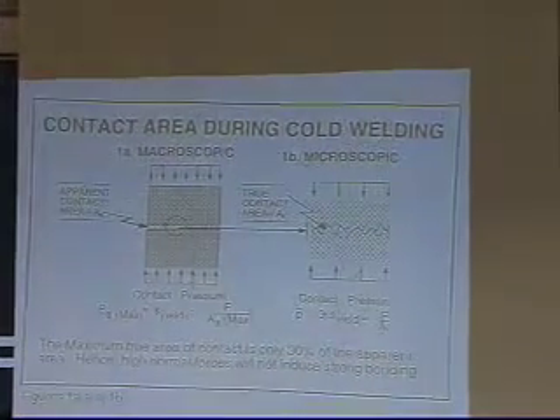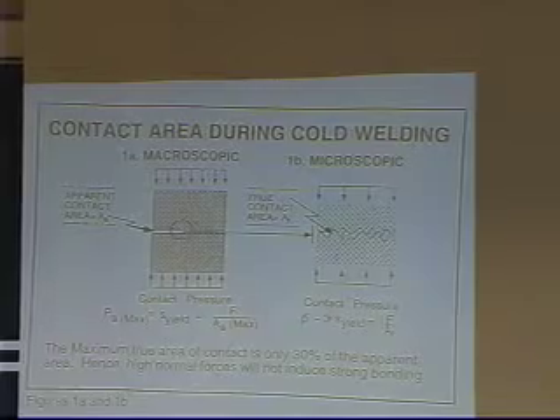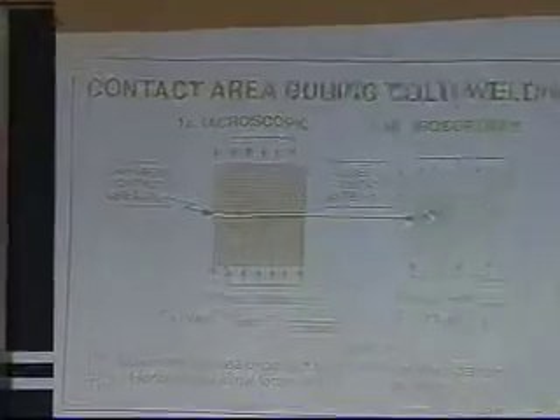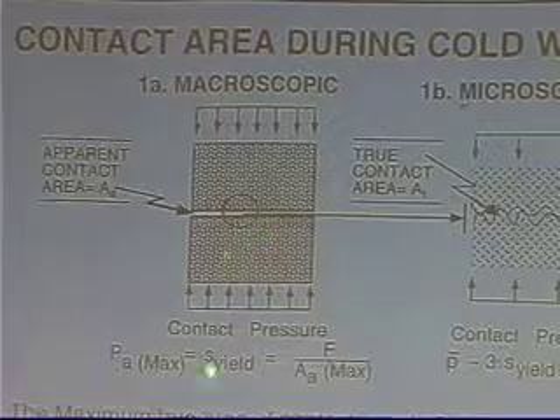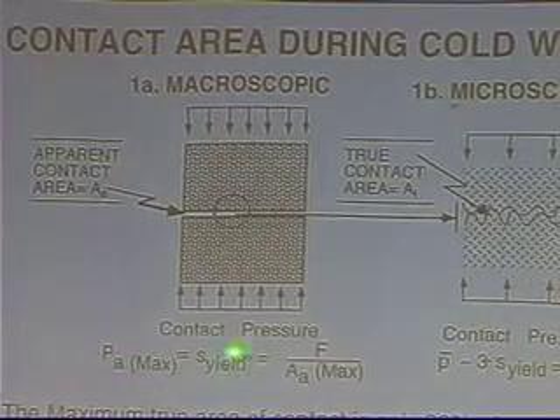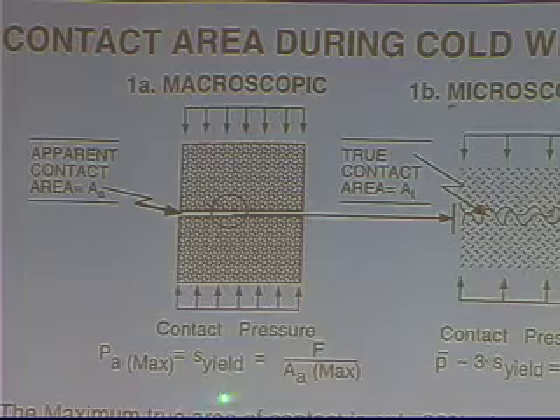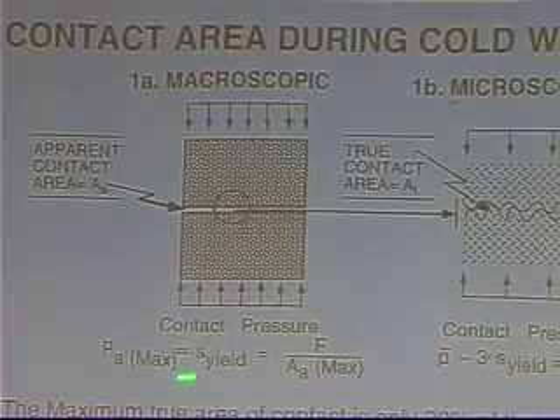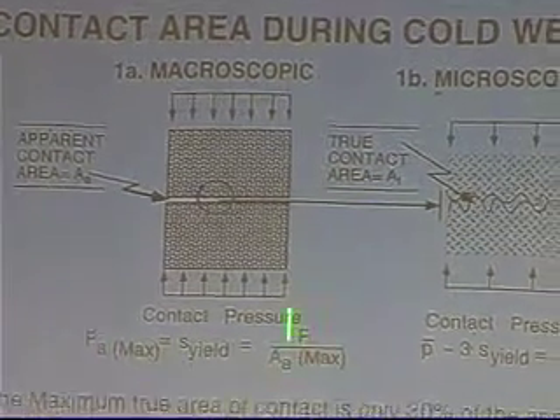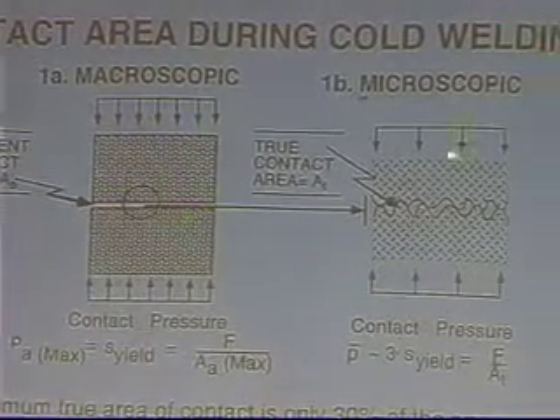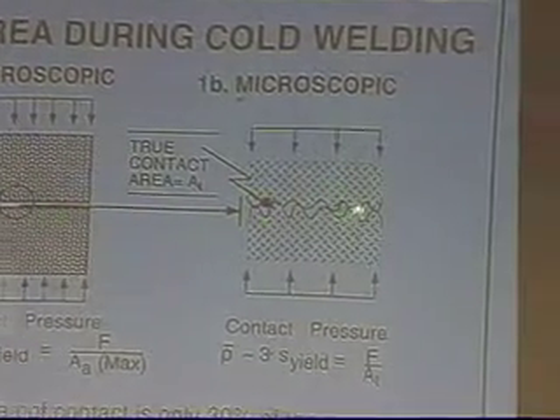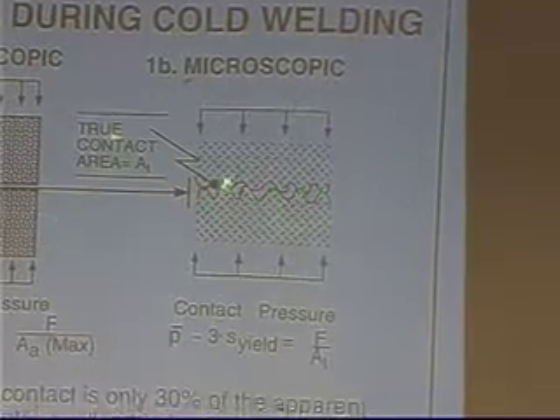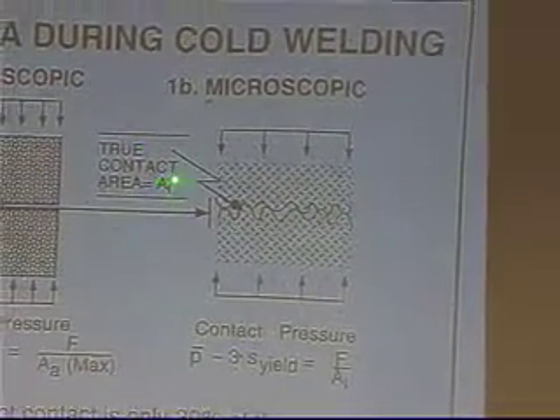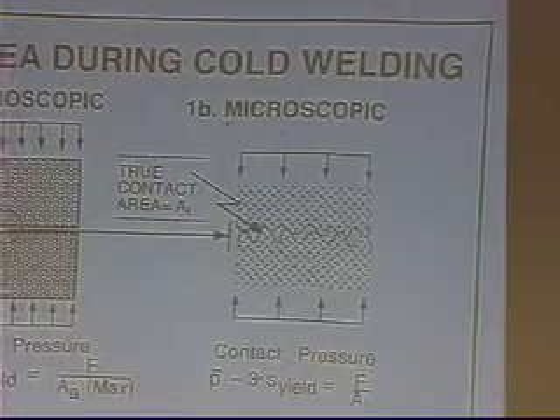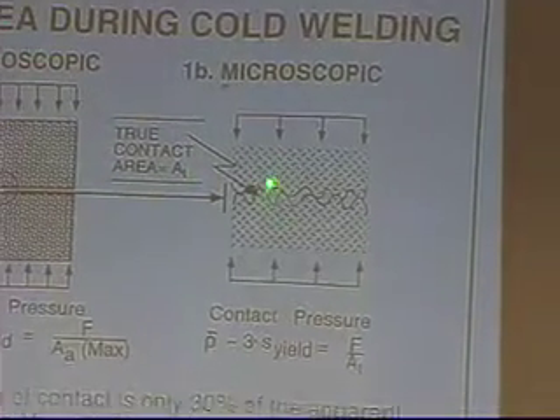Looking at the contact area during cold welding, macroscopically, we think of flat surfaces, and the area of contact is some area A, and we have a contact pressure. If we go to the yield strength of the material, using the civil engineering definition here, the yield is the force divided by the area of the flat surface. But microscopically, we have this rough area of contact. True area of contact is A sub T for true. Apparent area, A sub A. And true area is much lower.